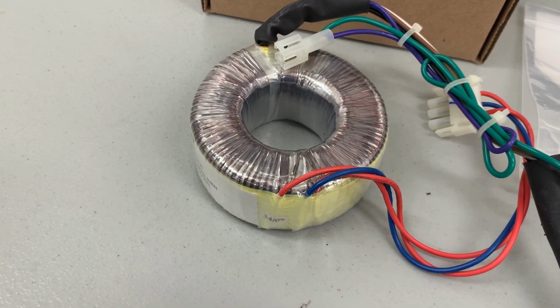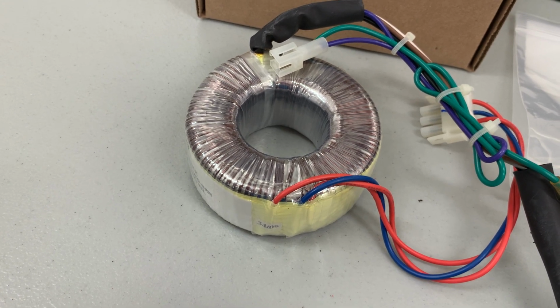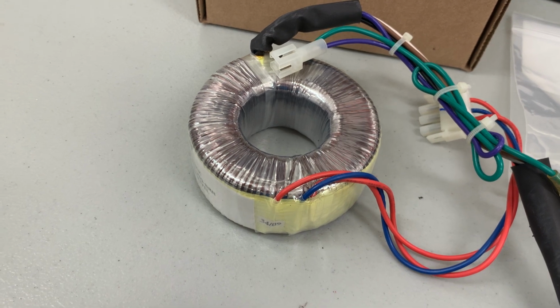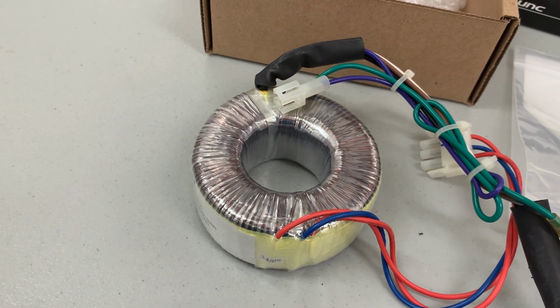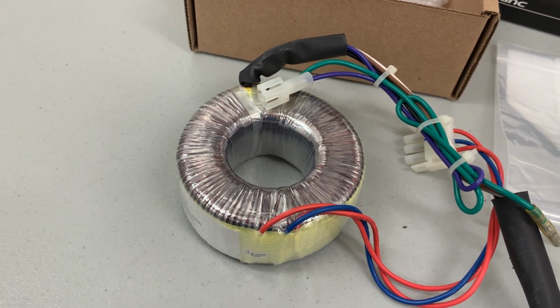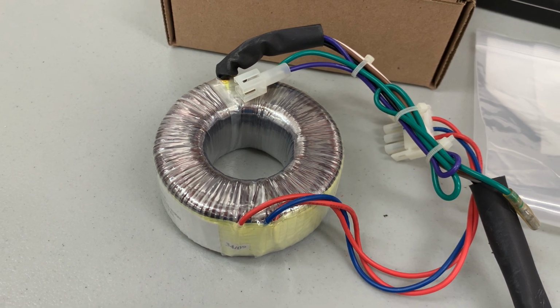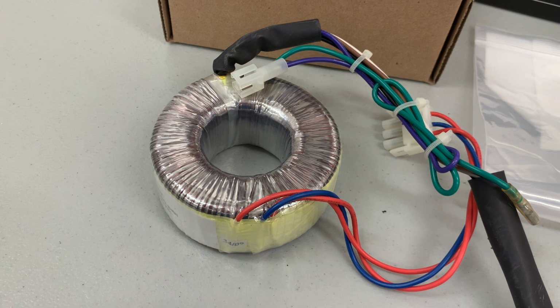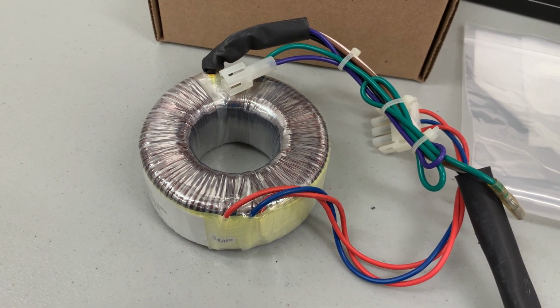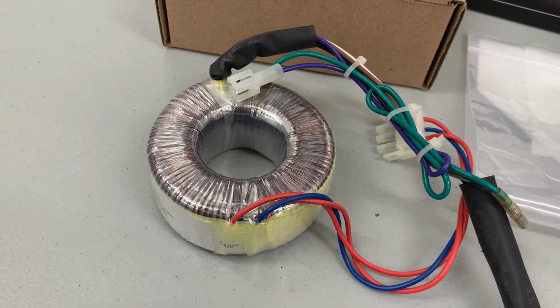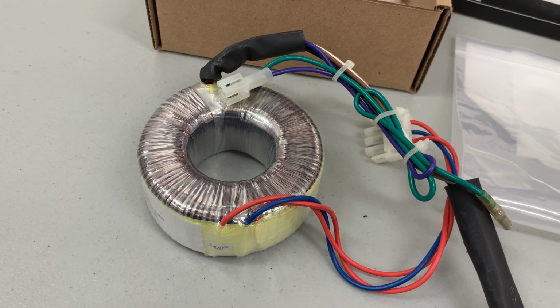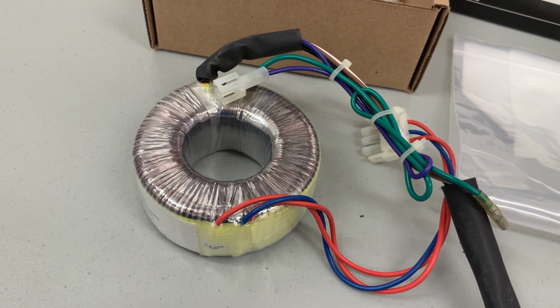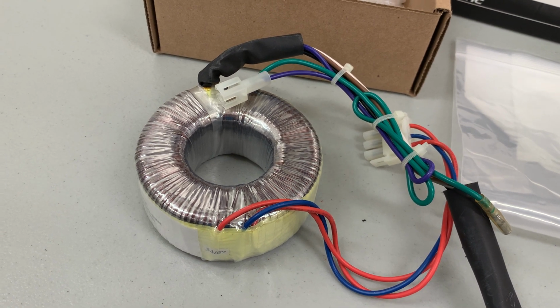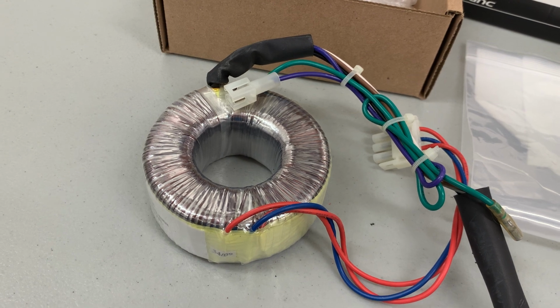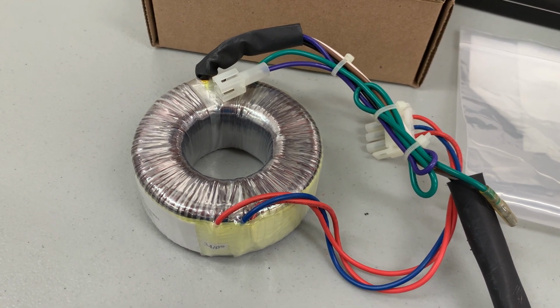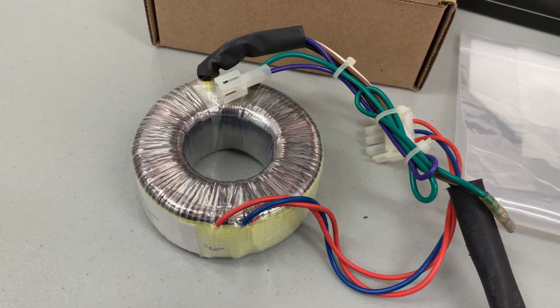That's the final thickness of that wire, and then it was allowed to cool to room temperature at a certain rate. And the slower the cooling rate, the better the annealing. So it means that the crystalline structure of the metal can form much better. And there are different casting techniques for copper, like the Ohno casting or OCC casting, and all of these are special forms of annealing with specific rates of temperature dropping back to room temperature, and as a result the crystal structure of the copper is much more uniform and has much better high frequency properties.